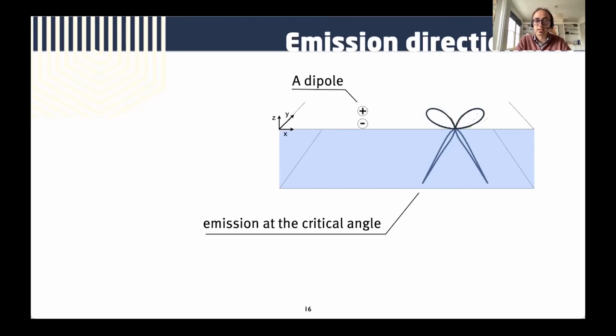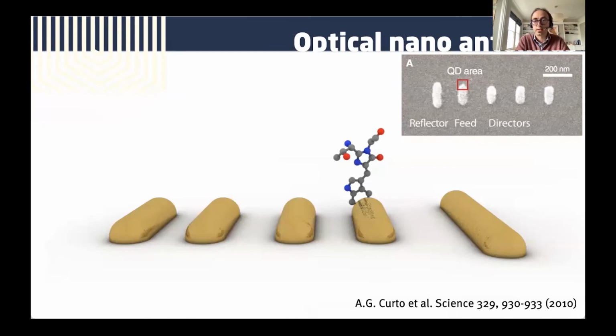So what's happening here is that the light goes into the glass and never escapes, and so we don't have much signal. And this is an experimental problem. Now, if you were to embed the material in a homogeneous medium, then you still have a spherical wave coming out from the dipole, which would be very hard to collect because it would be spread in all directions. So you really would like to be able to communicate with the emitter, send light from one direction and receive it from the emitter. And the way we do that is by using nanoscale antennas.